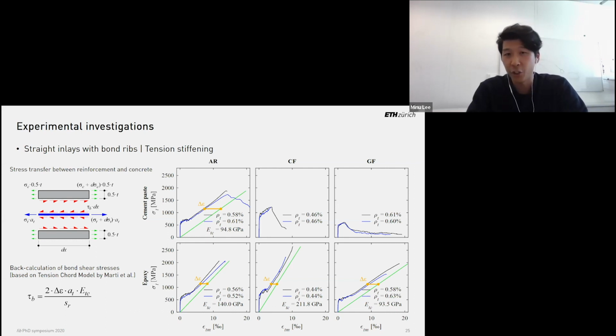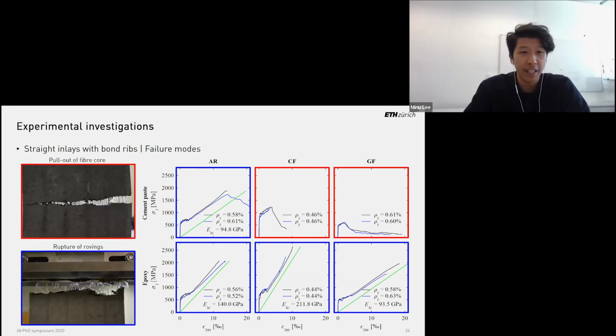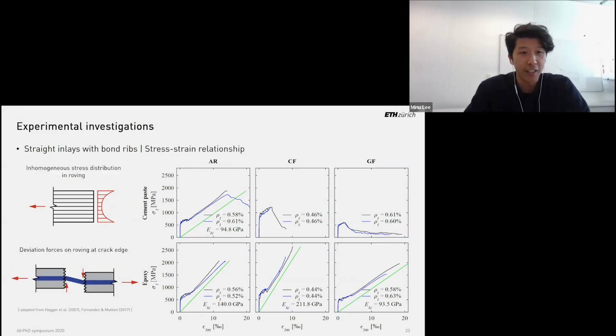It will just break eventually. And therefore, for the glass fiber rovings, once a crack forms, you really get this deviation at the crack edge, which will just cut through the glass fiber. And since the cement paste could not penetrate into the roving, it also cannot protect the fibers in the core of the roving, and therefore they just broke prematurely.